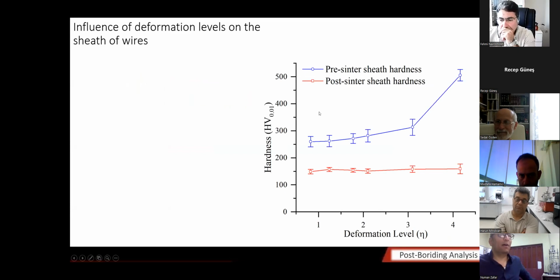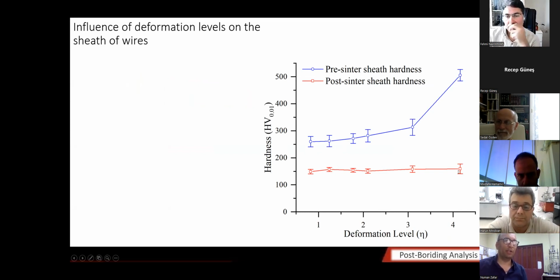Here is the hardness of the sheaths. As the deformation level increases in the pre-sinter state because of cold working, the sheath hardness also increases. But after the wires are subjected to the boriding treatment, the hardness of the wires is reduced, and they eventually show the same hardness because all wires are individually subjected to boriding treatment.